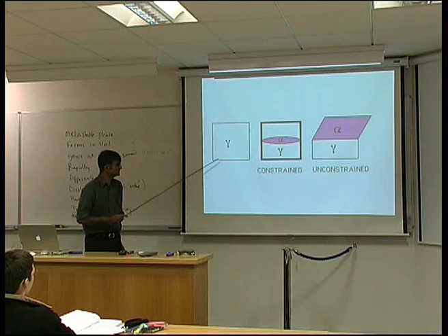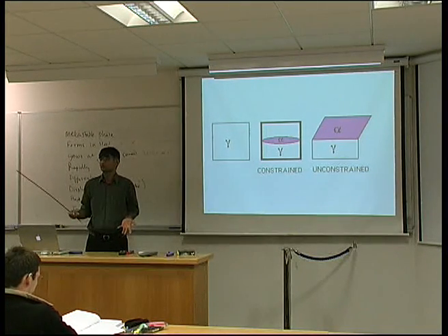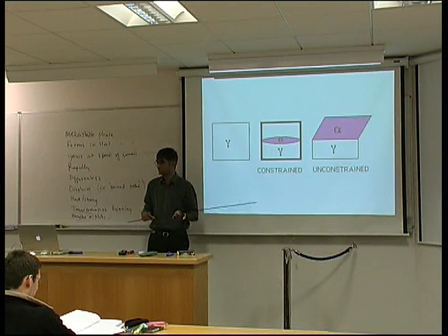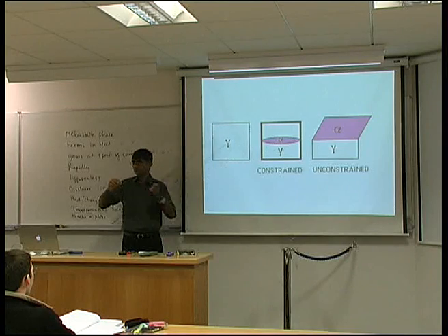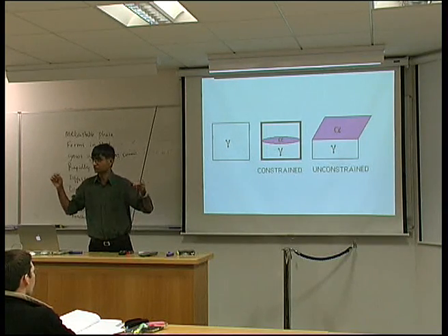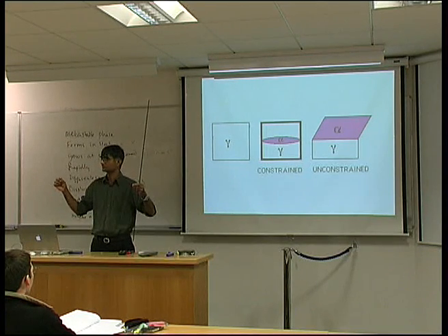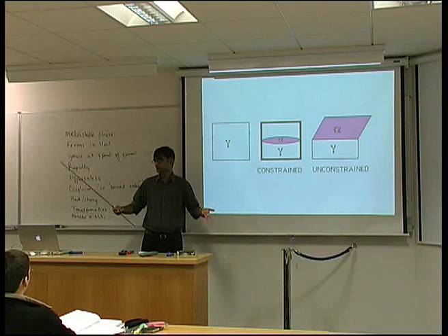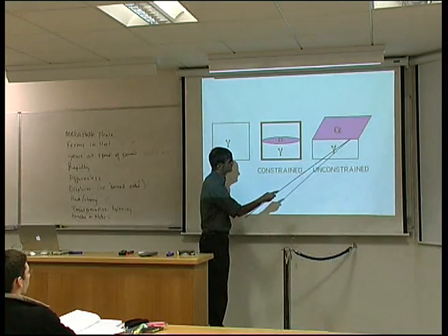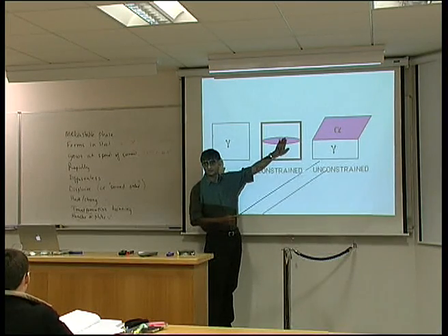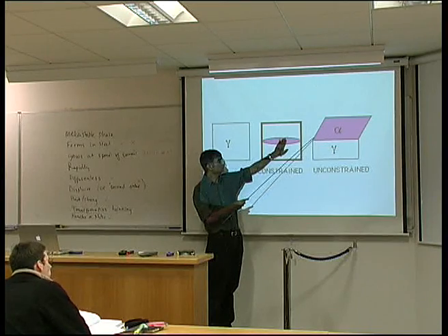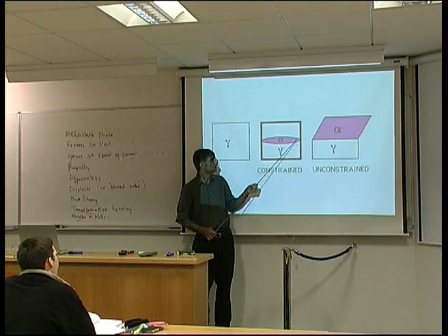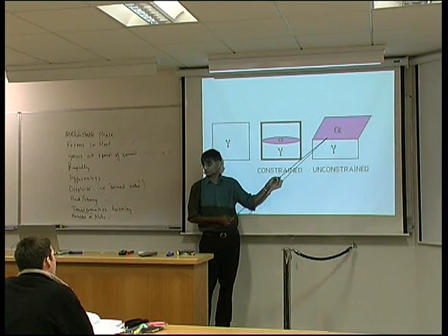Now, if I start with a crystal of austenite, which is present in bulk metals, so it's surrounded by lots of other crystals, in other words, it is elastically constrained from deforming, then when martensite forms, it forms as a thin lenticular plate. Lenticular means lens-like, so it's sharp at its ends, rather like mechanical twins. But if this is a single crystal of austenite, which is surrounded by air, in other words, a fluid, then you will see a flat interface like this, because this shape arises in an effort to minimize the strain energy associated with the change in shape when you change the crystal structure. So let me explain to you roughly why this shape minimizes the strain associated with this shape change.